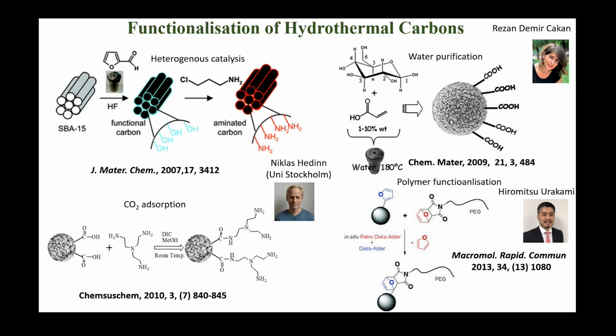So the nice thing is, as I said, you can add templates, you can nanostructure them, and because you have these functional rich groups on the surface of these hydrothermal carbons, you can functionalize them, for example, with amine groups, and then you can turn these amine groups into carboxylic acid groups. Then you can turn this carboxylic acid group even to more amines, or you could use the furan chemistry to really do Diels-Alder reactions onto the apparent structure of these materials.